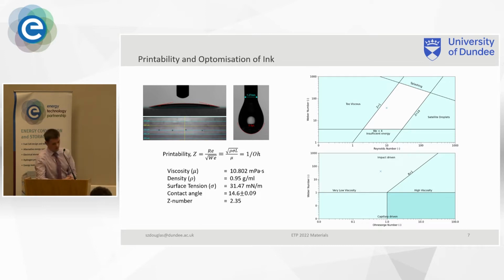On the right graph there is another printability measurement of what happens as the droplet lands on the substrate. If the spreading of the droplet is controlled by impact-driven forces or capillary-driven forces. Our ink, for drop-on-demand printing, which our printer is, you want to be within the impact-driven, which means as it hits the substrate, it spreads. Its maximum spreading is defined by those parameters, and then it'll follow by a bit of relaxation, which will eventually be by capillary-driven. But initially it's impact-driven, which is the range you want to be in.